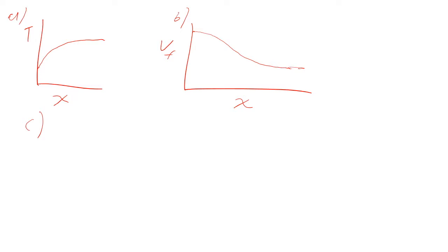So if the surface has more free volume than the bulk, the surface would pull on the interior of our hypothetical cube, because the interior is going to contract more, and the exterior is not going to contract as much. Since we don't have voids forming, that's going to lead to a tensile stress in the surface and a compressive stress in the bulk.